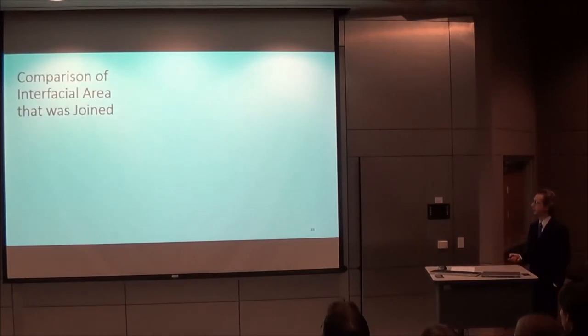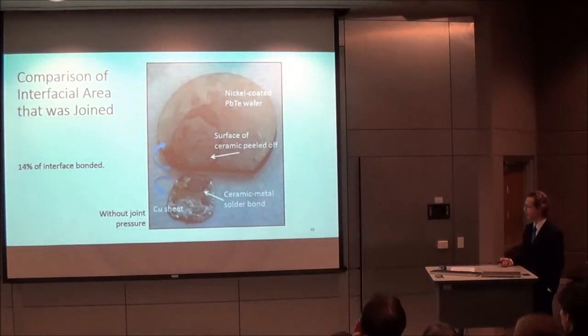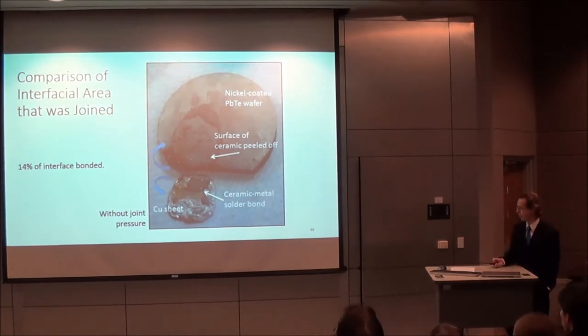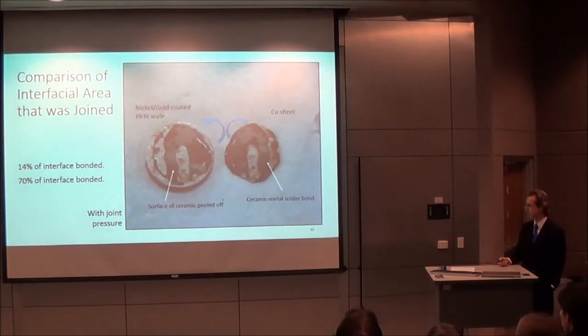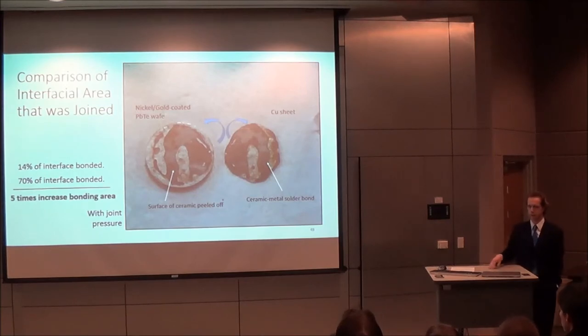So a comparison of the interfacial area that was joined shows that with a previous joint made without the use of pressure on the joint itself, a relatively small proportion of the interfacial area, which is represented by the surface area of this copper sheet, was actually bonded. However, with the use of a pressure applicator, a significantly larger portion, represented by this dark area, was actually bonded. And so there's a 5 times increase in bonding area that was achieved by using the pressure